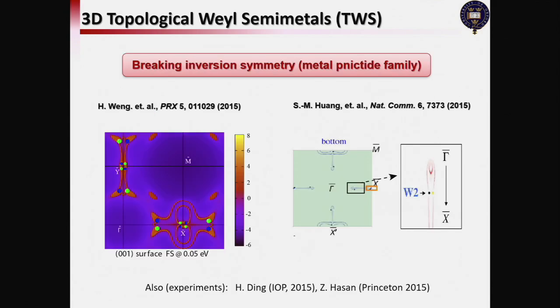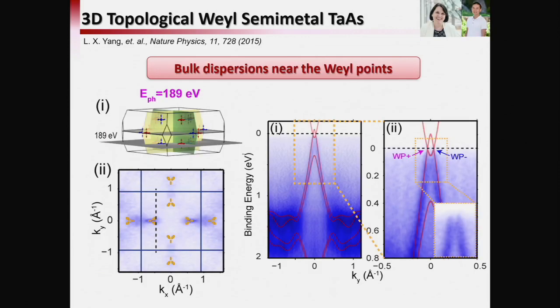And about 3 or 4 years ago, another family of materials was proposed that break the inversion symmetry. Then we jumped into those and found that indeed we were able to see the dispersion of the Weyl fermion, and you can see there's almost a linear dispersion. This is a bulk band, but the tip of the dispersion is no longer a single point. It's an M shape, and there are two Weyl points separated. Right, a little bit.